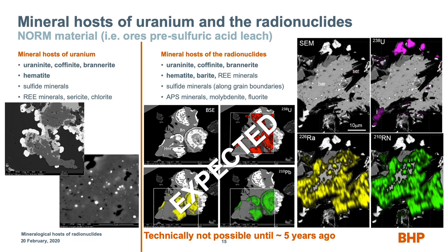Then we go over and we say, barite, why do we think it contains radionuclides? Very small, micron size again, 10 micron scale bar. There's barite here with all kinds of bright white minerals in it, and those happen to be little galena particles. There's some coffinite. We're going to look at the uranium-238, and you can see the hot spots are in the coffinites, which you kind of expect. Well, if it was uranium mineral, we'd expect the radium, the lead-210 and polonium-210 to be sitting at the same place that uranium is. It's clearly not, and it's hanging out all around that barite. Why?